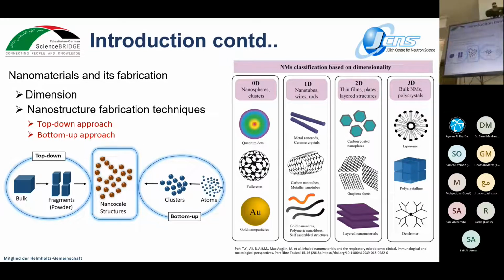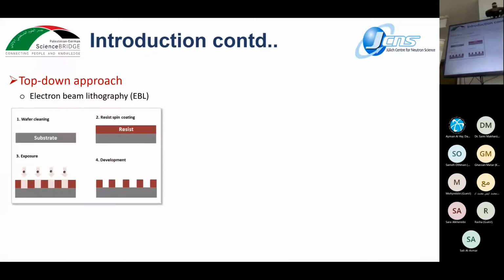But for the bottom-up approach, we actually start with a very small particle, and use an assembly method until we can produce a nanostructure. The top-down approach, as I said, is such as electron beam lithography, and using it we can end up with nanoscale regime particles. So during my research, I had to prepare such a pre-structured silicon substrate with nanometer width grooves.